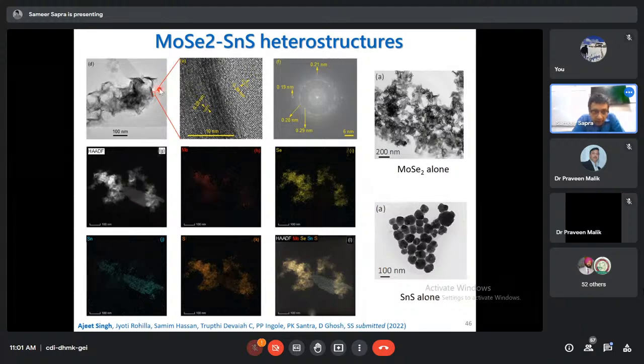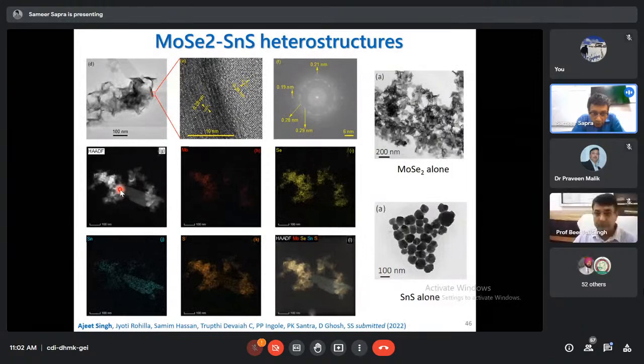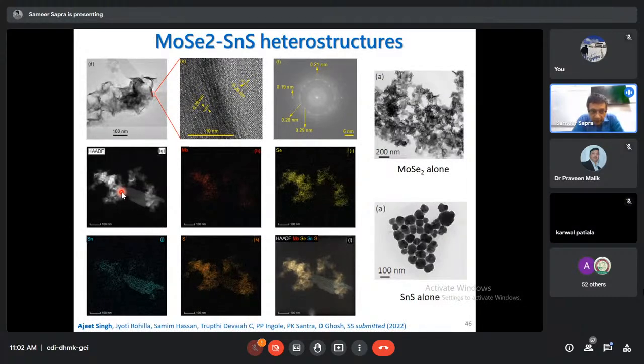So you can see this. These flat things are the tin sulfide. It's very evident from all the HAADF elemental mapping. You have tin in these flat regions. And molybdenum selenide, of course, is still my crumpled sheet. But tin sulfide, if I make it alone, is more like these spherical platelet-like small nanoparticles. Molybdenum selenide is the crumpled thing again. But when you make it in the presence of molybdenum selenide, it starts to grow from some nucleating spots, which we believe are the edge sites. We still don't have evidence for that, but they then make these very nice monolayer sheets. And these are very lovely things. You can see all the atoms very clearly for tin sulfide.